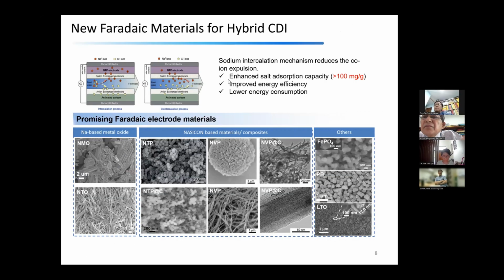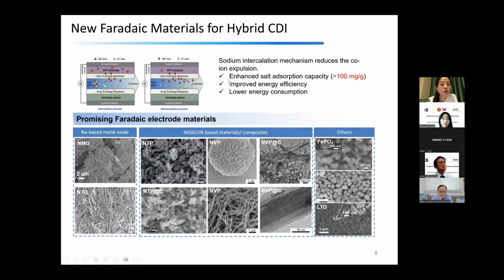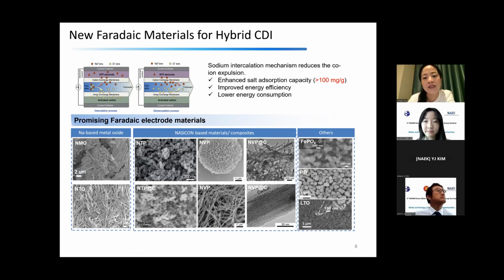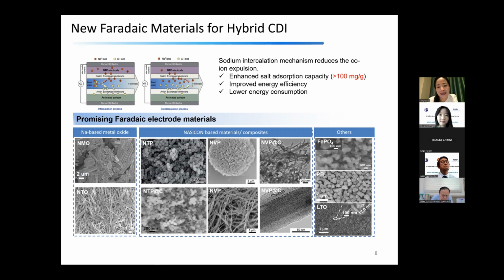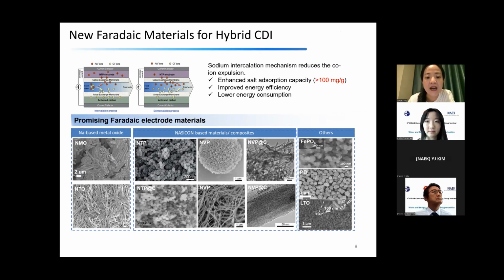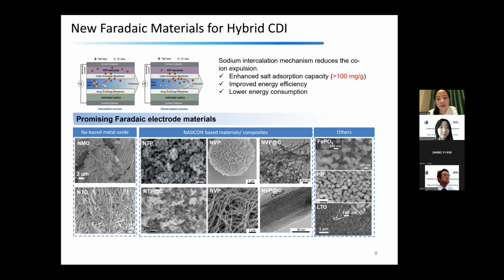We have also figured out a new group of Faradaic materials for this type of CDI hybrid electrode. For example, a sodium intercalation mechanism to reduce the co-ion expulsion. And then we have identified NASICON, which is sodium-based, and also a sodium-based metal oxide.